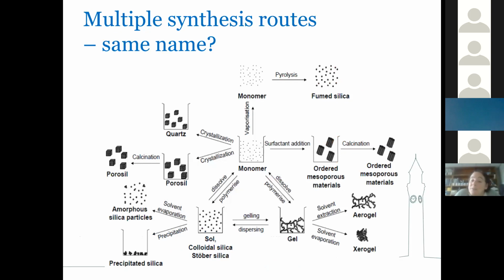Another challenge, as if there wasn't enough so far, is that for many materials there are many different ways to produce the material, yet they are all called the same thing. This is just an example for silica, which is a very widely used material with a whole range of applications. Starting from the same starting material, there are a number of different synthesis routes to make silica. Through surfactant addition, you get ordered porous materials. You can do it through crystallization processes, which lead to different sorts of crystal structures, through dissolution and polymerization, gelling, dispersion, and so on, plus through pyrolysis, which is a heat-based process. All of these have very, very different structures, but they are all silica particles.